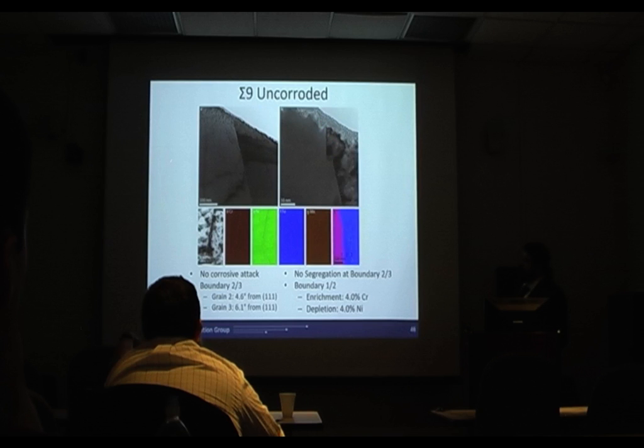So what was actually happening was that the sigma 9 occurs when two sigma 3s meet. Between the left grain here and the right grain here is a sigma 9 orientation relationship, but that boundary appears to have dissociated into this nano twin array.